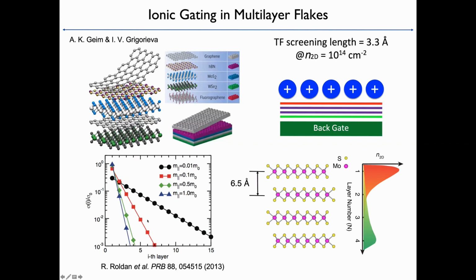So theory tells us if you take a reasonable effective mass of the electron, for instance 0.5 m0, 90% of the induced carriers are actually accumulated right at the surface. So only 10% goes to the second layer. If we go to the phase diagram of the system, this means this layer is very conducting in the metallic state and superconducting state, while the second layer is barely approaching a metallic state. So you can well isolate this one from the rest. And if you cool the system down, all the transport is coming from the top layer.